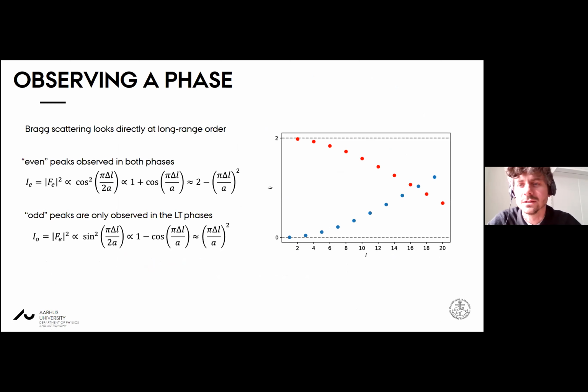Okay, so how do we determine this? What we have to do is measure the structure. So we have to go to a probe which is measuring the structure, which is X-rays. And traditionally, people have looked at this process using Bragg scattering. We all know that we can use Bragg scattering to determine the structures of crystals. And if you go through your maths, which I'm not going to do here, you can work out quite easily that for a dimerized system or a dimerizing phase transition, there are two types of peaks. There are even peaks, which are present independent of the magnitude of delta. And these are the peaks that correspond to the high temperature phase. And then there are odd peaks that are present only when the system is dimerized.